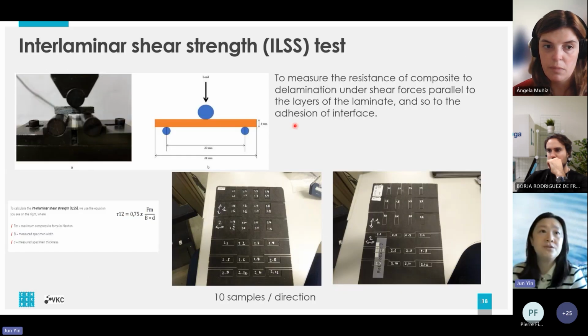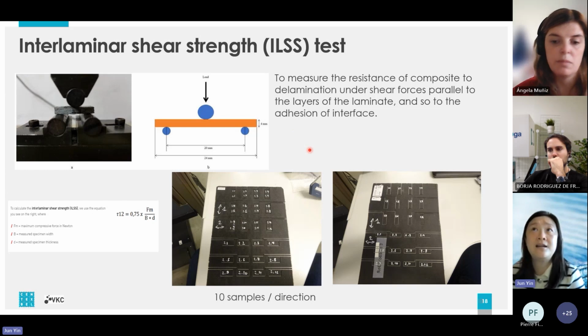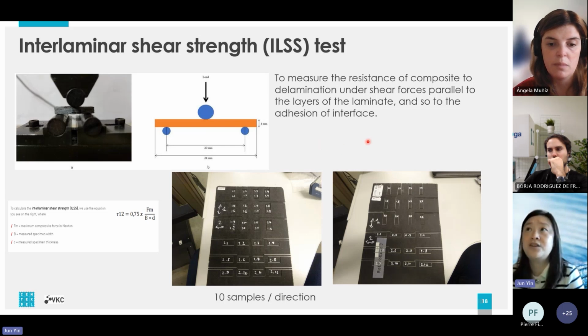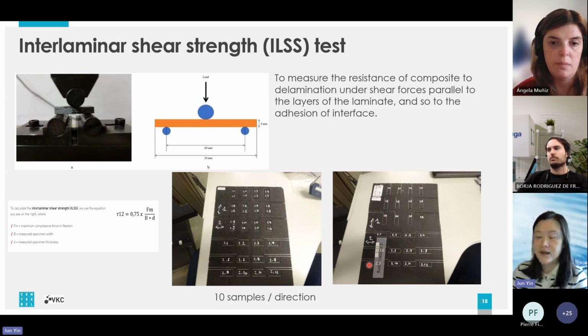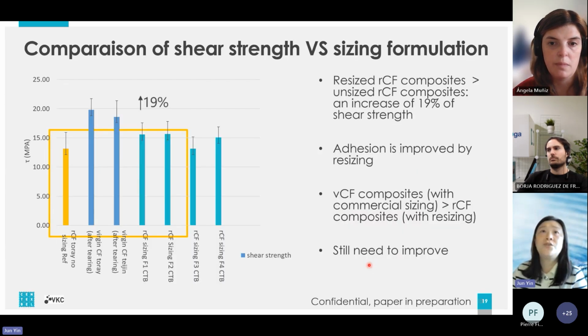Then all these samples are sent to the interlaminar shear strength test, ILSS test. So it's to measure the resistance of the composite to delamination under shear forces parallel to the layer of the laminate, and so the adhesion of the interface. For each sample, we test 10 samples per direction. Then we calculate the average value of the shear strength. So now I show you the first result we have.